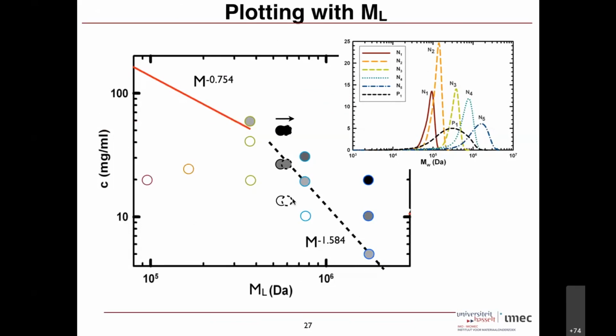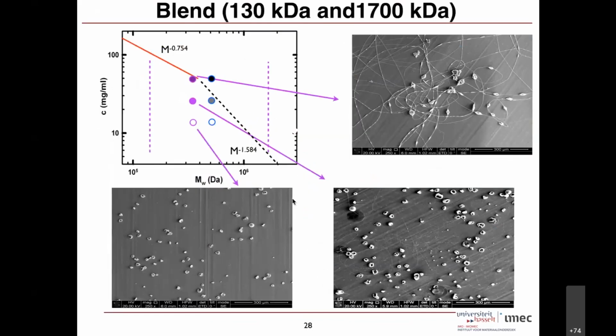We can do one more trick. We can make a blend of very low molecular weight and very high molecular weight: a lot of low molecular weight and a very small amount of high molecular weight. Here it is. So I took a line here, that is the molecular weight 130, and that's the molecular weight 1700 kilodaltons. If I combine them, my effective molecular weight would be this one.